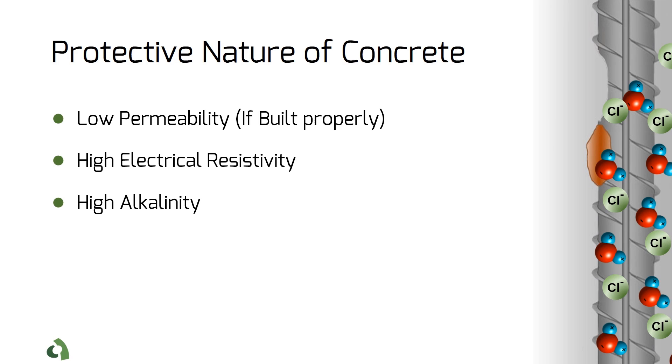A very basic explanation is that the ingress of chloride destroys the protective oxide layer on the surface of rebar. This eventually destabilizes the protective film over the reinforcement, which eventually leads to the initiation of corrosion.